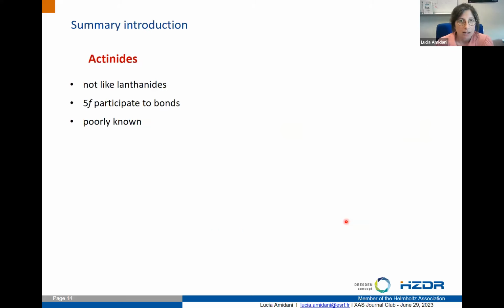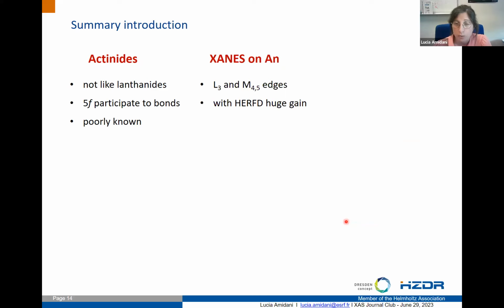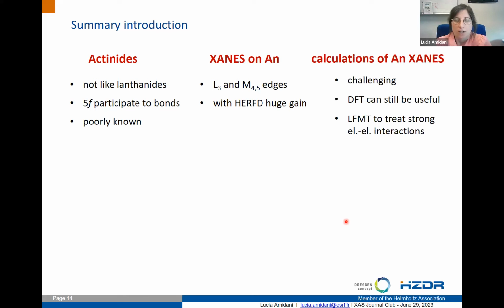So this is the introduction I wanted to give. Briefly to summarize: actinides are not like lanthanides, the 5F electrons can participate in bonds, and they are poorly known. We can address these elements with spectroscopy at the L3 and M4-5 edges, and with HERFD we have a huge gain. In terms of calculations, they are challenging, but DFT can still be quite useful, as I will show you, and we have the ligand field multiplet approach, which is very well suited to treat stronger electron-electron interaction cases.